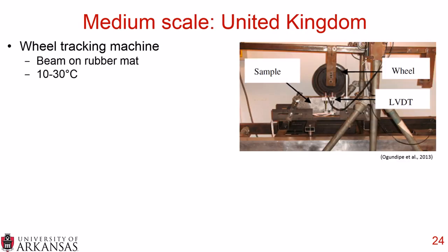Now moving over to the United Kingdom, they used a medium scale wheel tracking machine, and you can see an image on the right where there's a wheel running over a sample and you're measuring deflections with an LVDT. The beam is placed on a rubber mat, and they tested at 3 temperatures: 10 degrees Celsius, 20 degrees Celsius, and 30 degrees Celsius. For the materials, they used anywhere from a 40 to 80 millimeter overlay.